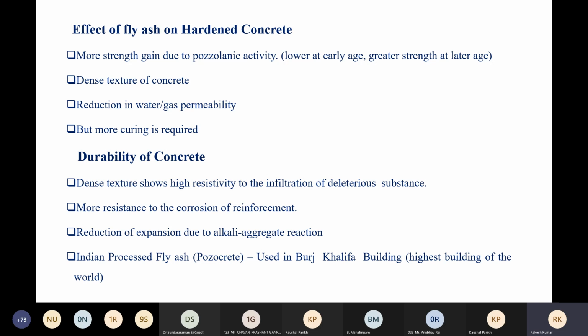What is the effect on the durability of concrete? Dense texture shows high resistivity to infiltration of deleterious substances. So whatever substances affect the body of concrete, their infiltration is reduced. More resistant to corrosion of the reinforcement, because of the dense texture. Due to that, chloride, or you can say moisture, will not go near the reinforcing material, and due to that corrosion will not start. Reduction of expansion due to alkali aggregate reaction, because calcium hydroxide is already consumed by the pozzolanic material, so the alkali aggregate reaction is also reduced.